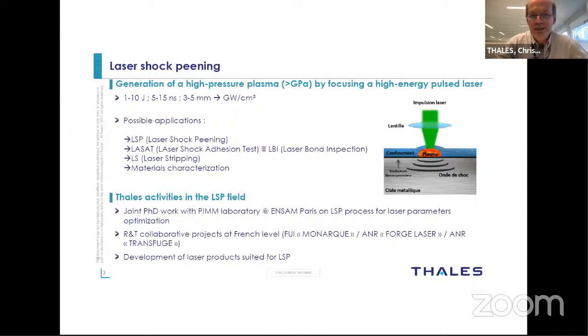So this process is basically, sorry for the French words in the scheme, but basically the idea is to use a high energy short pulse laser, very short pulse. We talk about nanosecond pulses. So the idea is to send the pulse to a metal part. With the high peak power, you are going to vaporize some material and create a plasma. You have to confine this plasma in order to have a maximum effect, to optimize your effect, and it will generate a shock wave into the material. And it is this shock wave which is important because it will create constraints in the material. It means it will be compressive stress, and this compressive stress is very useful for the lifetime of such parts.